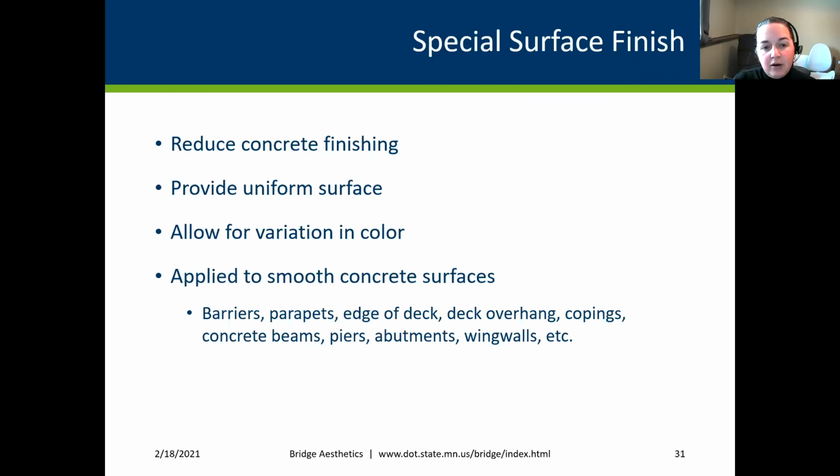But now our coatings are such that they actually have chloride protection in them and they serve other purposes. So they do save us money. They reduce concrete finishing. We don't have as many requirements for some of that finishing because those special surface finishes have those textures. They give a uniform surface. They allow for that color, so that kind of follows more what the public would like to see.